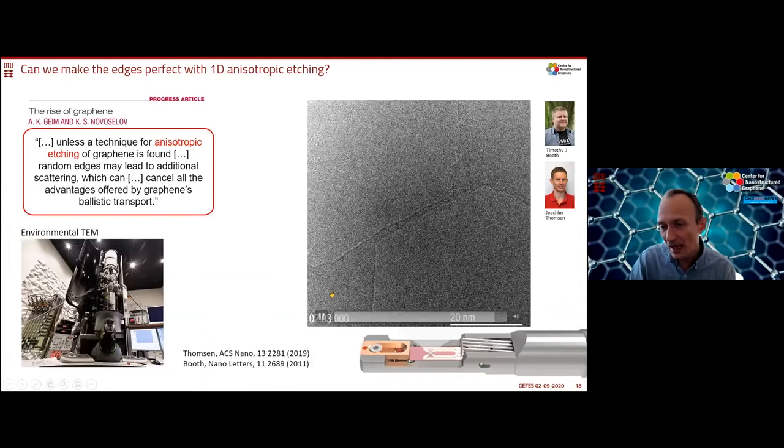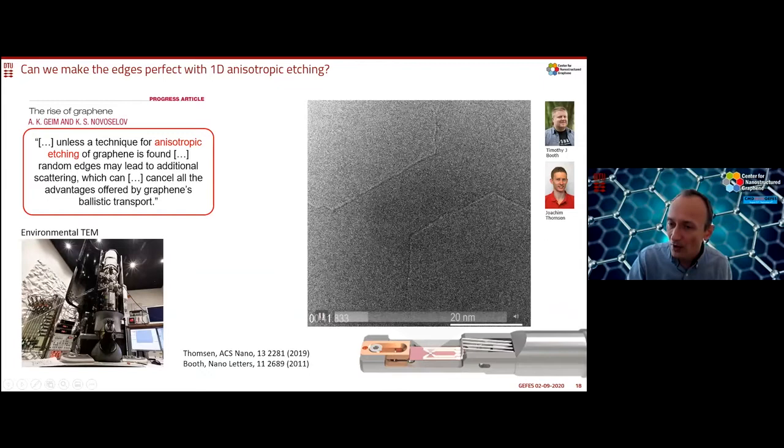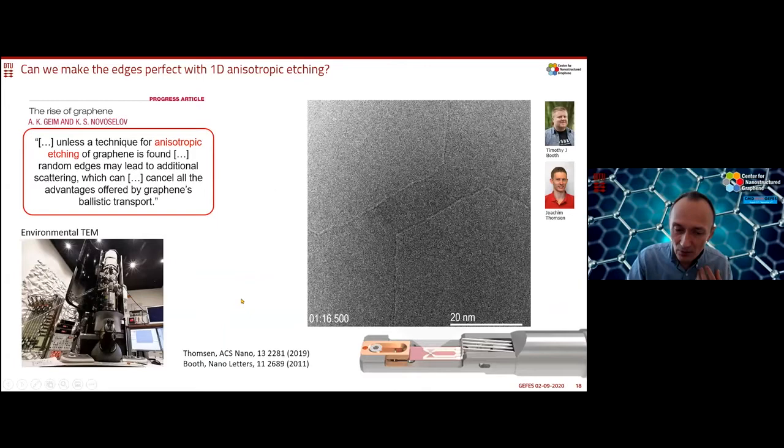So it's not that much better than with lithography, the one I showed you before. But the interesting thing here is that it follows the crystal directions. This is something we also did in a different way, which we call the Pac-Man method, where instead of just having oxygen etching the graphene, we use silver particles that catalyze carbon atom removal at high temperatures inside a TEM. So when you use silver particles, they act as small garbage collectors